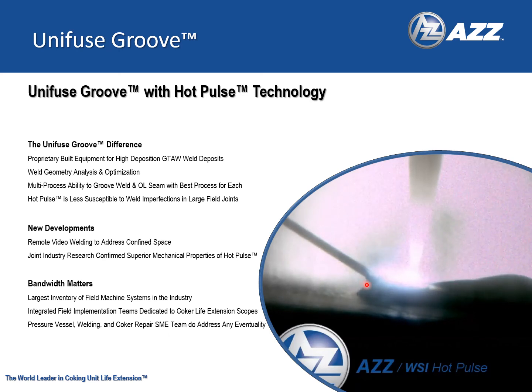Perhaps the most important feature is the agitation in the puddle caused by the intermittent dabbing of the wire. This puddle agitation reduces the propensity for lack of fusion and accelerates degassing of the puddle, which reduces porosity. The combination of these features allows us to deliver the mechanical properties achievable with GTAW at the deposition rate of FCAW.